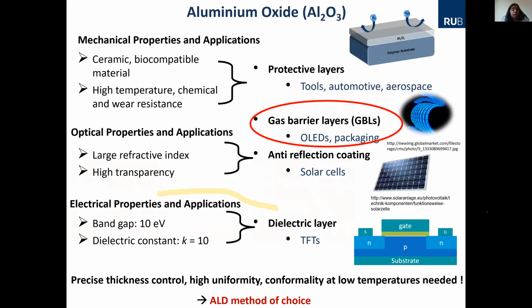So here's one example, which is a very common material system, aluminum oxide, that you all have experienced. We know aluminum oxide can exist as bulk, and it has very good mechanical properties. It's a ceramic, it's biocompatible, and also very resistant to temperature and chemicals, and wear resistant. This is something very important. So it can be used as a protective layer, for example, in tools or automotive applications or aerospace, especially in the airplane. You have a very thick coating of aluminum oxide, which can withstand extreme conditions, especially when the flight takes off. You have a change in pressure, temperature. So all this material is very relevant for that.